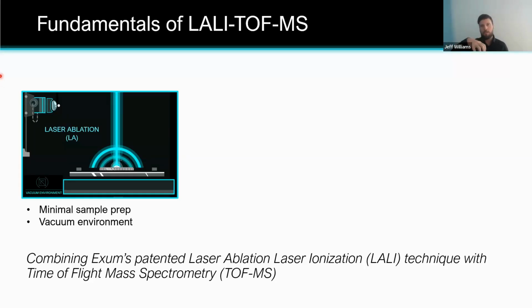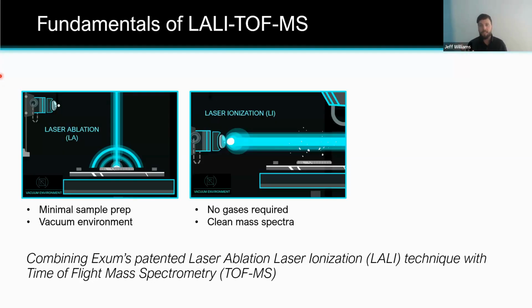So once we have this neutral particle cloud, the next step that we have to do for our mass spec is we have to ionize it somehow. So instead of sending those particles and atoms through a tube to another plasma, what we do is we take another laser and we come across and we ionize that neutral particle cloud. So we basically put such a high density of photons in there that it excites an electron one time, then excites it again. And now it's so far away from the nucleus that now we have an electron and an ion pair.